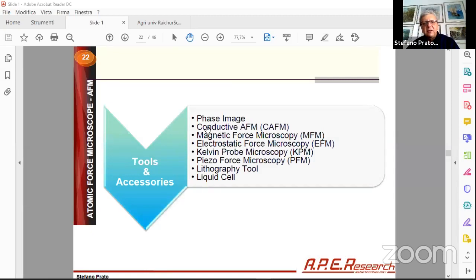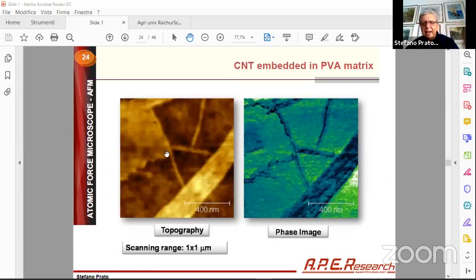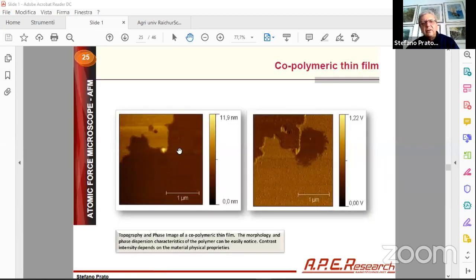Phase image, conductive image, all those. When you do AFM, you do a topography. But at the same time, you can also acquire other parameters, okay? For example, this is a plastic embedded with a carbon nanotube. This is the topography, and this is the so-called phase image, okay? Phase image allows you to understand if the material is the same. From the topography, you don't know if this material and this material are the same, but with the phase image, you can say, no, it's not the same material. There are 2 different materials. Again, here, you have the topography and you have the phase image. This material is different from this material, again.